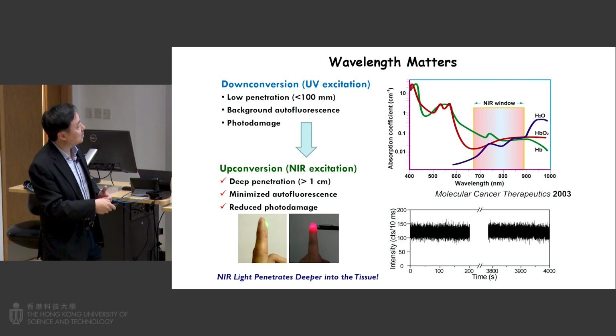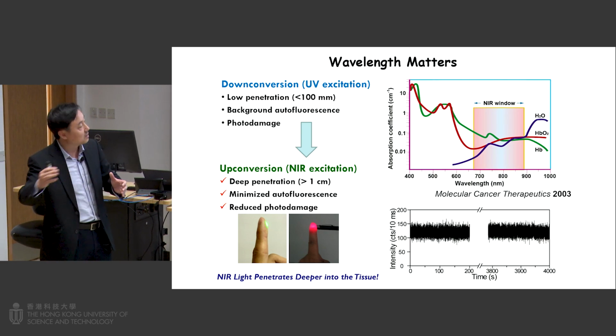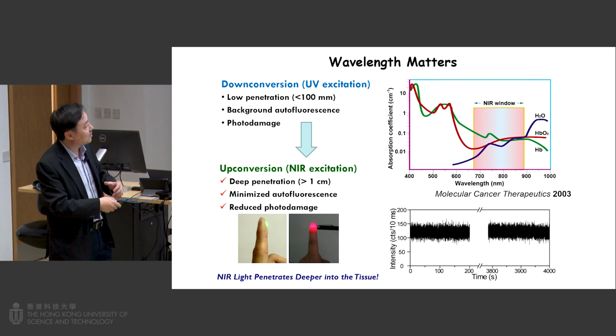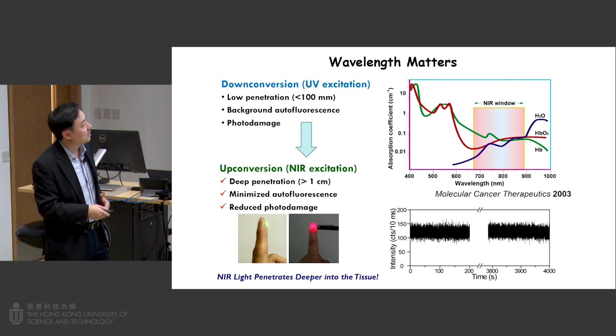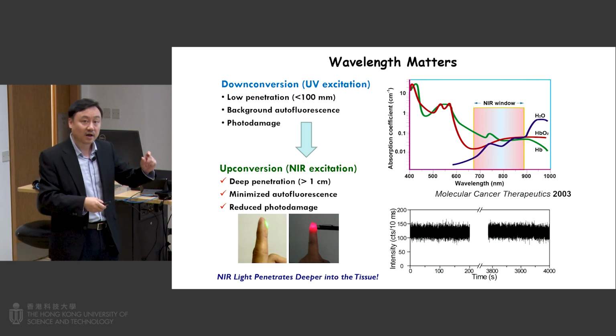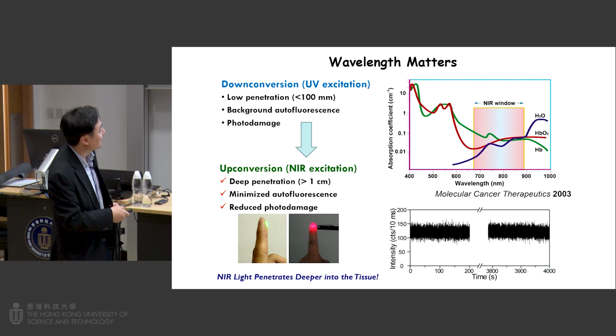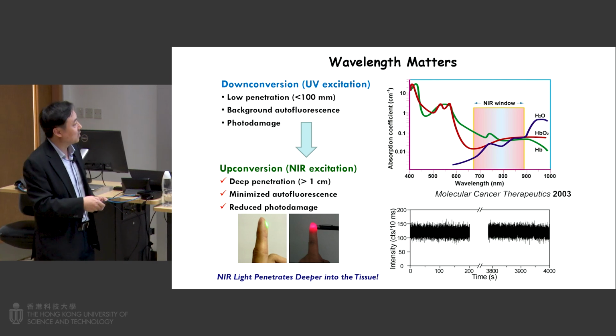The other thing is that if you're using near-infrared light as excitation, as we talk about upconversion, near-infrared light gives a much better penetration. The penetration here, of course, is showing the red excitation. Compared to the green excitation, red has much better penetration.